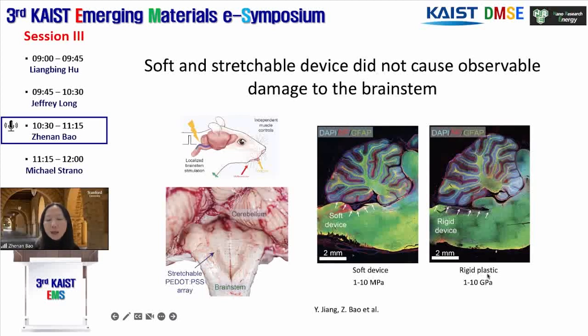But with the plastic substrate, even though it's flexible, it has a much higher modulus than the soft devices. Even after implantation for 1 day, the histology already shows cutting of the device into the brain. At the same time, we observed the mouse tends to be paralyzed or have much reduced movement after such implantation due to the damage of the brain.